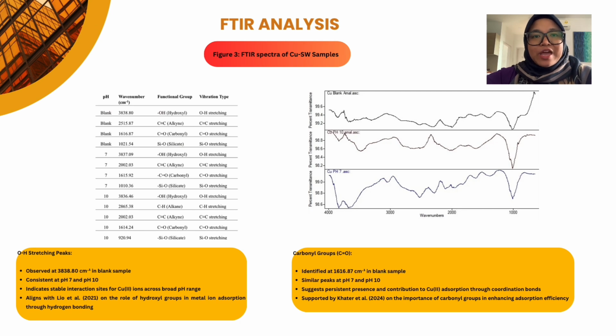Next, let's examine the FTIR spectra of the copper SW sample. For the copper SW sample, the FTIR spectra show consistent hydroxyl stretching peaks around 3,838.80 and the carbonyl groups at 1,616.87 across all pH levels. At pH 10, additional peaks for alkyne groups at 2002.03 and alkane stretching at 2,865.38 were observed. This indicates that functional groups on the composite interacted with copper ions, which enhanced the absorption process.